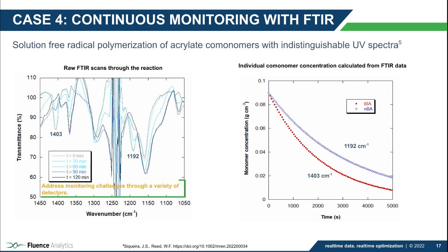Acrylate monomers can have almost identical UV spectra, so individual concentrations are not possible to calculate with that technique only. But slight differences in the monomeric structure lead to different vibrations in the IR region that can be tracked, like it has been done here for the isomeric pair tert-butyl acrylate and n-butyl acrylate. From the two characteristic absorption peaks indicated on the plots, their individual concentrations were calculated and composition can be tracked.